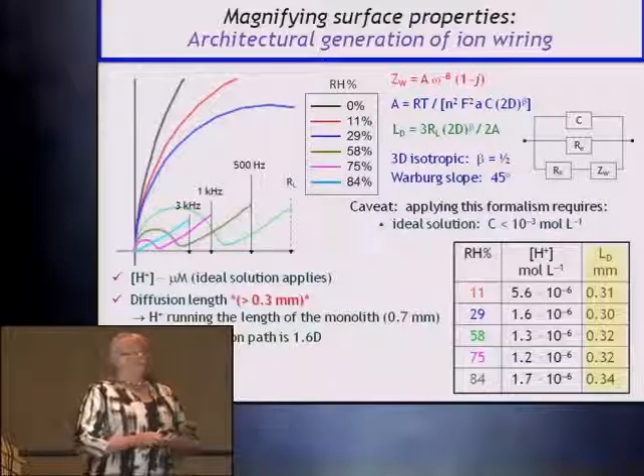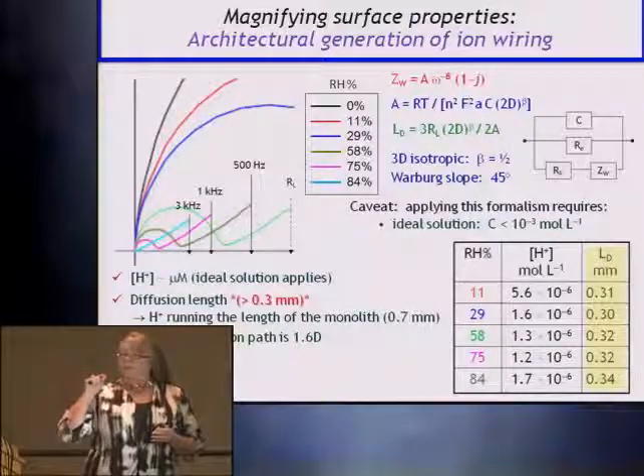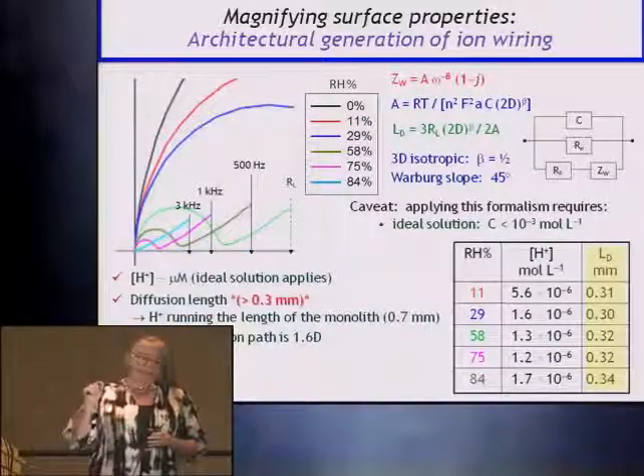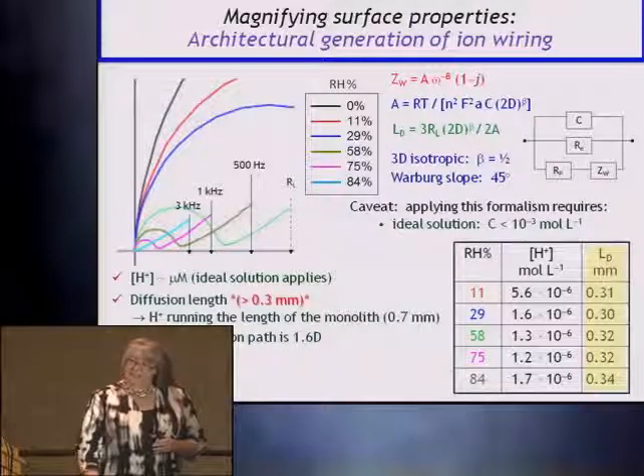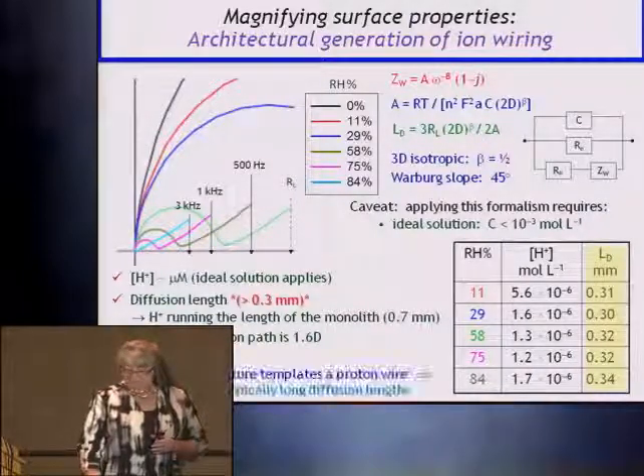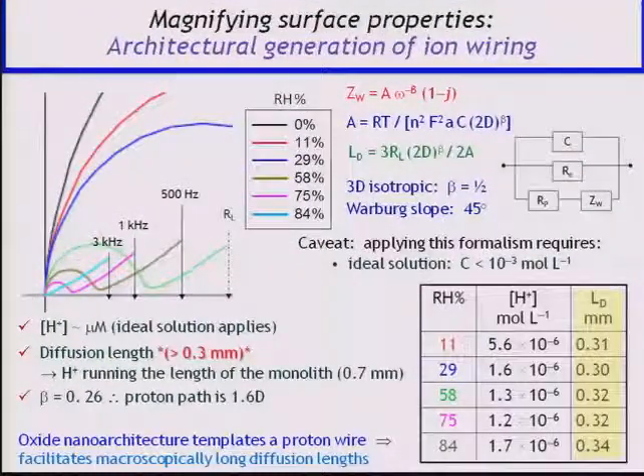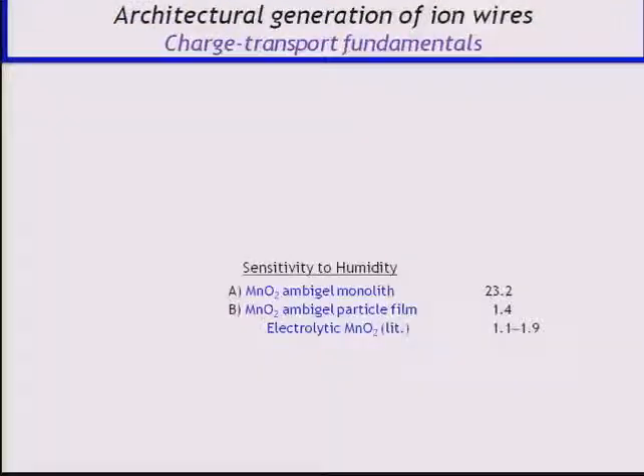Aerogels are fractal. So the proton is, of course, trying to find the shortest path it can between the two electrodes. Not quite 1D, but definitely not the dimensionality of the scaffold. So we've got a proton wire at long lengths because of the architecture. If we have this monolith and chunk it up, as many people would if they had a nanopowder and wanted to do a sensor to humidity, they would form a particulate film. And when we chunk this up, we drop the sensitivity to relative humidity by a factor of 15, right where it is in the literature for electrolytic manganese dioxide.